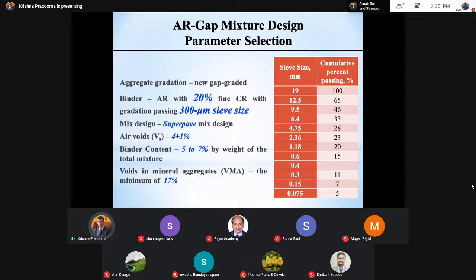We actually tried with state-of-the-art equipment. We found that a blend of 20% will be ideal for us, and that is the definition of AR also, right? Minimum 15%. So we were able to capture that. Now we also came up with the gradation of the rubber. So 300 micrometer. That's something very important you people should understand. And we came up with the Superpave mix design, which makes it much more robust and strong. Why? I'll tell that in just a minute.